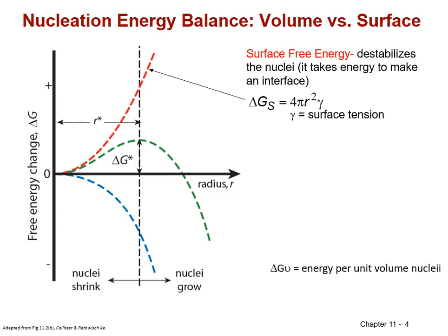Well, the change in energy in the system with the change in particle size will simply correspond to the surface area of that spherical nucleus times the surface energy, which is the energy per unit surface area there. Actually, this would be surface energy, not surface tension. So 4 pi r squared, very important squared here, times the surface energy.